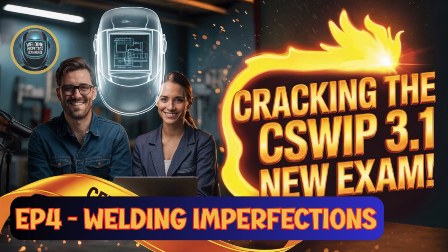For interrun fusion specifically, low arc current leading to a sluggish weld pool or too high a travel speed can be causes. And a lack of interrun fusion is bad because it also creates these crevices where slag can get trapped easily. So it's really about ensuring the weld pool is both hot enough and clean enough to properly melt and merge with all the surrounding material it's supposed to join.